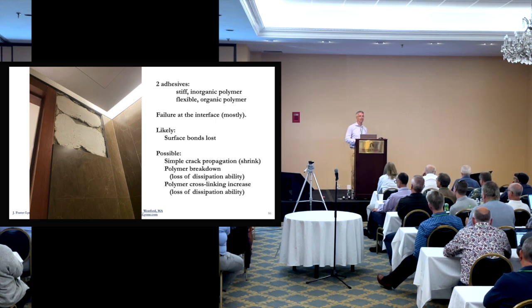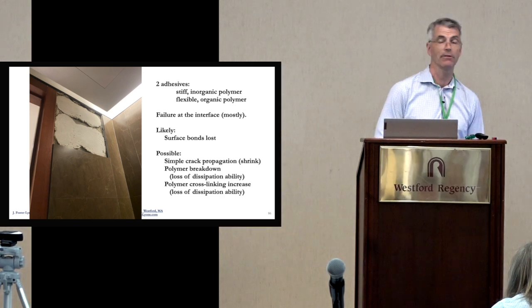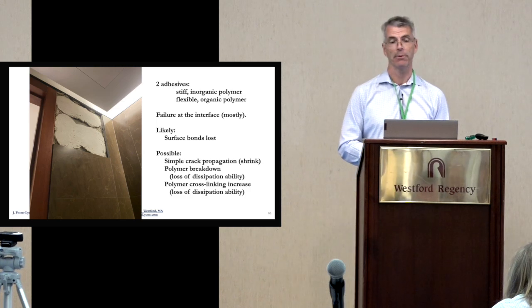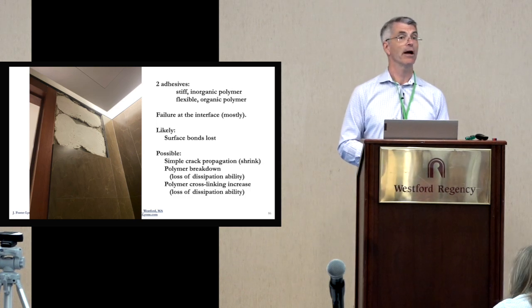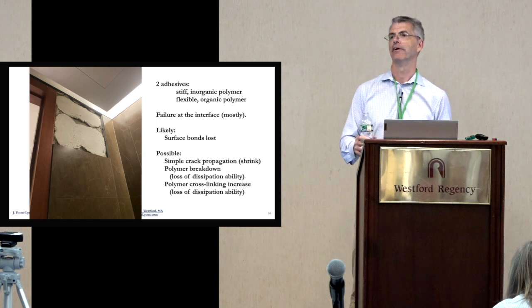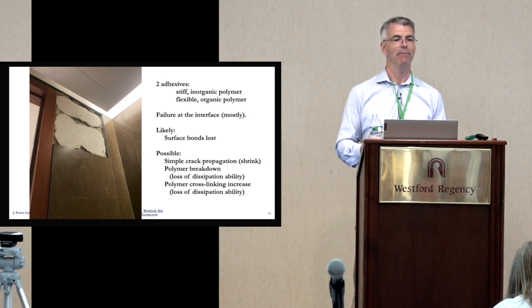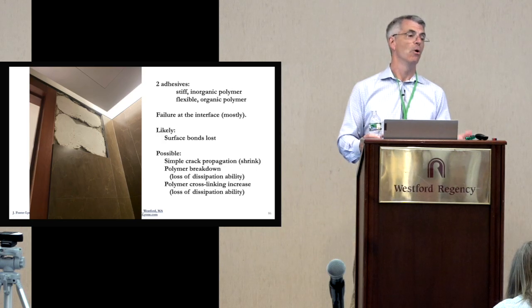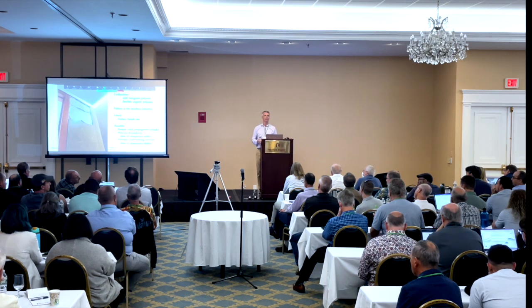So in this case, the failure is right at the interface, mostly. So it's most likely that the surface bonds were lost. But it's possible that some intermingling got clipped. It's possible that the polymer actually just totally broke down, so it lost its ability to dissipate crack propagation forces. Or it's possible that the polymer actually cross-linked more and became stiffer, and that stiffness became a real problem, or that it somehow created more and stronger surface bonds, which is a problem. You'd think more would be better. It's not. It's worse.